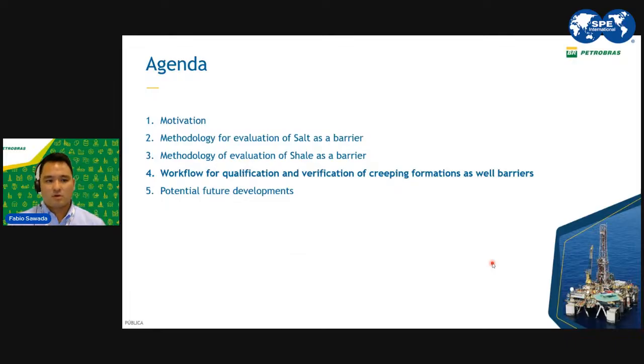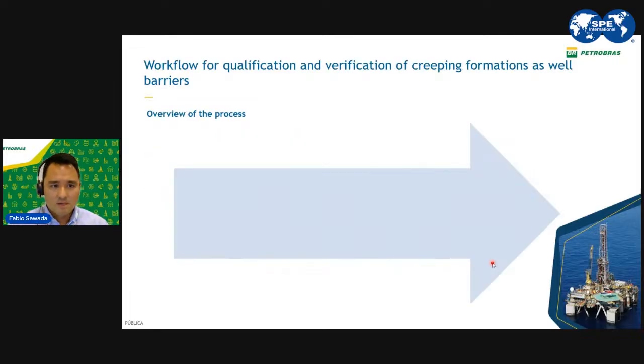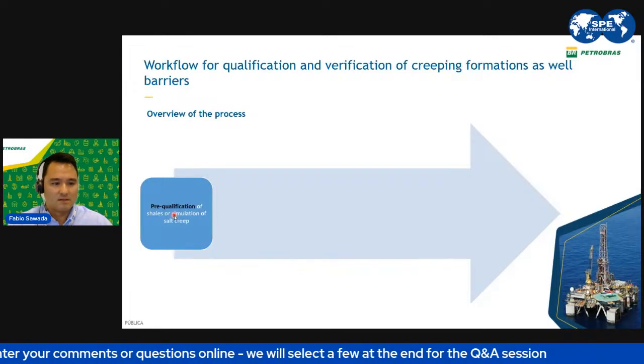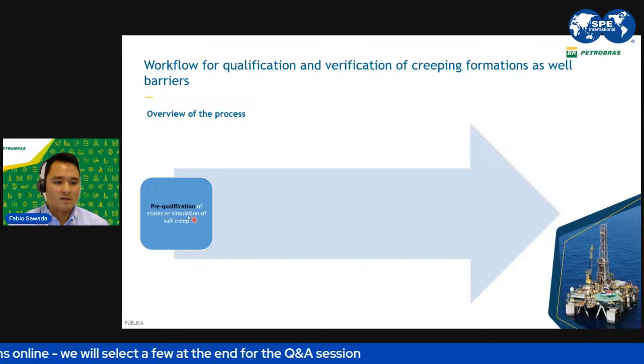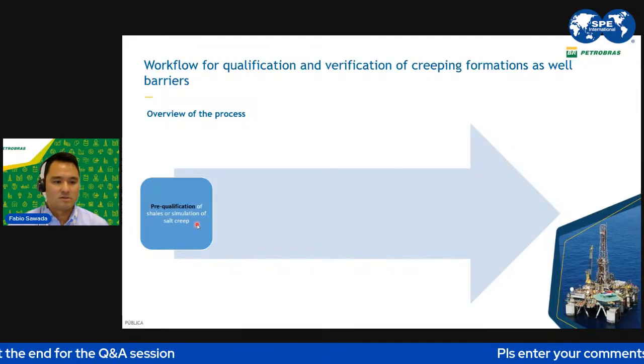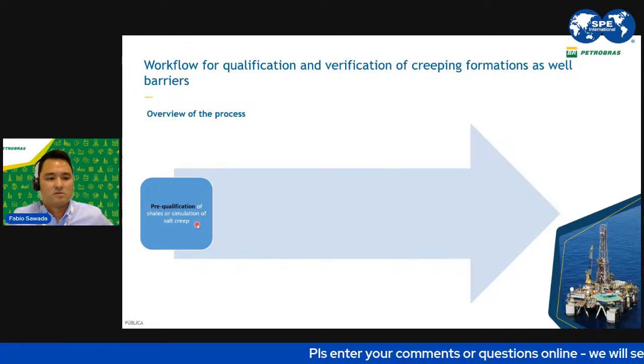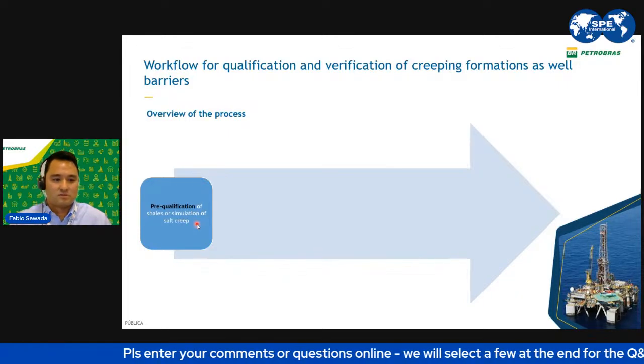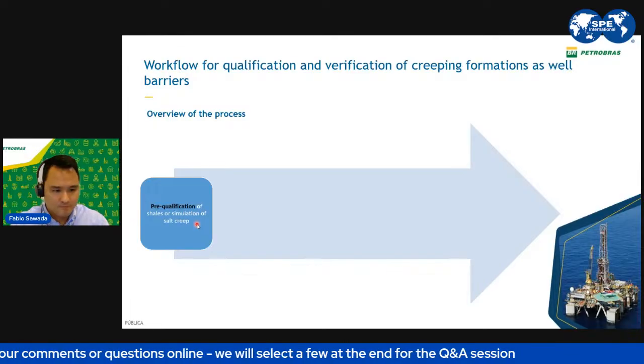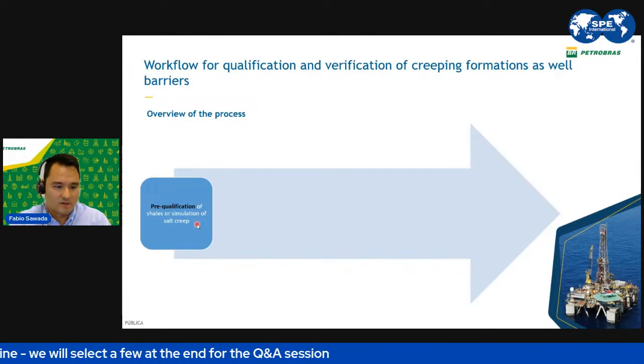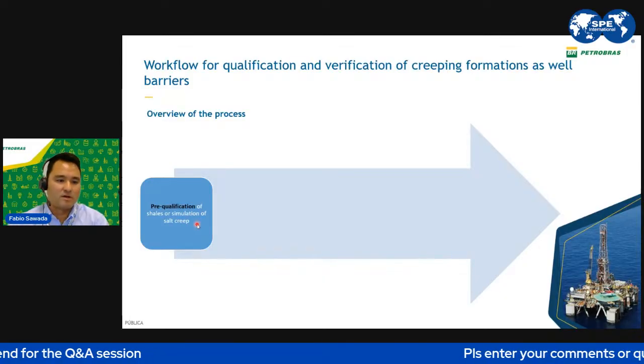So, a proposed workflow here for the qualification. We have an overview here of the process, where we start with the pre-qualification. That would be, in the case of shales, evaluating all those parameters that I showed before. We can do that before performing any bond logs or any pressure tests in wells. And also for salt, we could use the double creep model to simulate the conditions of the wells that we have, to see if the salt has the potential to form the barrier. We could use the ratio that we created here, for example, as something for the pre-qualification of salt.